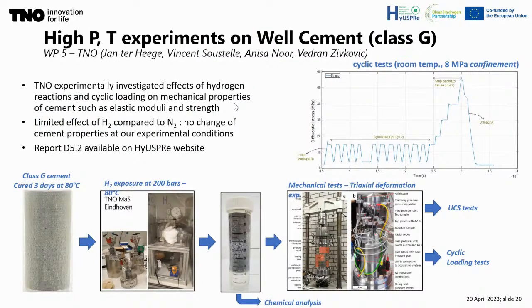So briefly about the cement integrity tests that were done at TNO and recently finished. What we did here is cure class G cement, prepared according to API standards. We exposed these samples to hydrogen at 200 bars at TNO in Eindhoven. We did chemical analysis and also mechanical tests with deformation, both unconfined compressive strength tests and cyclic loading tests. For instance, for the cyclic loading, you see an example at the top right here: first a cyclic loading test after initial loading, then step loading to failure, and then afterwards unloading.